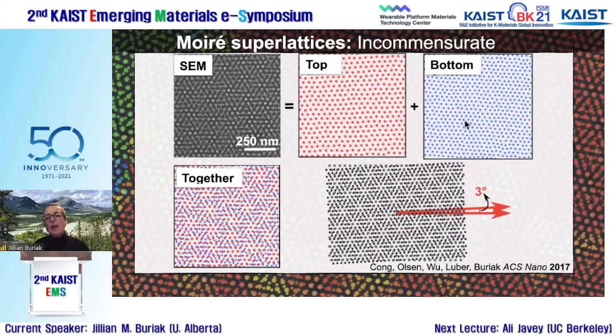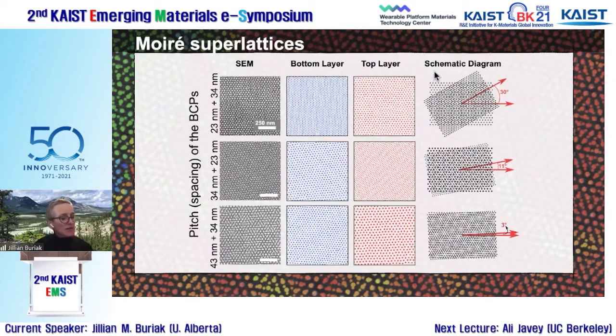You can put them back together, but once they're separated, what this allows you to do is to determine the angle of offset of these two lattices. And so what this showed is that the lowest energy configuration that the system could adopt under these conditions was to take on an angle of rotation of 3 degrees. And that's what gives you these Moiré superstructures. At the time, we had no idea what was driving this, or any predictive power at all to predict where these things were going to go. And so what Cong did was then take 3 combinations of block copolymers.